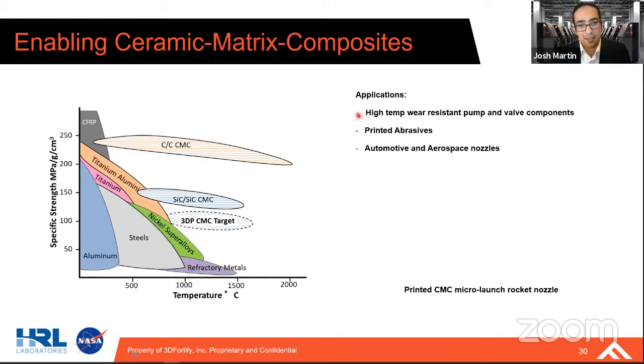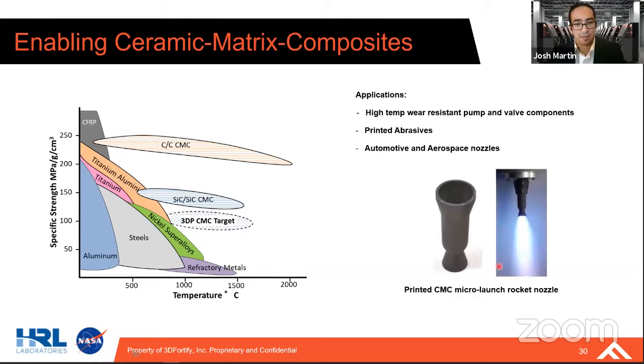And we're looking to take these unique materials into high temperature, wear resistant components such as valves and pumps, especially something in an industrial process that moves a lot of abrasive material at temperature in a very corrosive environment. It's a perfect fit for these materials. Also printed abrasives themselves, and even automotive and aerospace fuel injector nozzles. This is what a lot of this work has been funded to date at HRL to support, which is essentially printed CMC micro launch rocket nozzles. And so this really speaks to the level of performance that can be reached using this class of material.